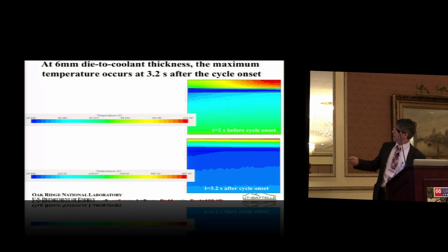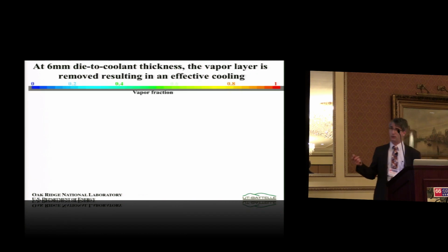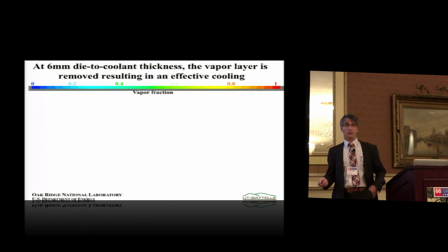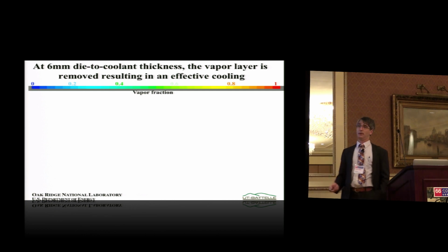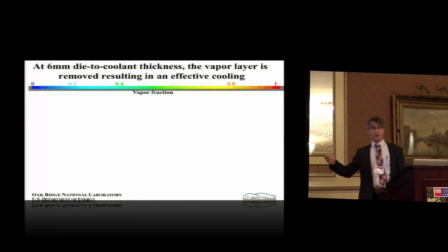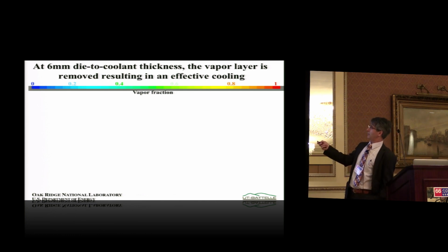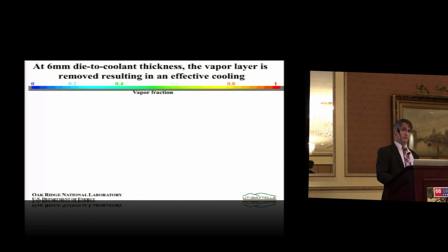For another configuration that we look at, again, here we have a smaller die-to-coolant thickness right here. If you can take a look at these temperatures, we came down from 790, I guess, to about 500. The die can reach up to 600. So it's a very acceptable number. Let's look now at, in this particular case, the last case. Again, color-coded blue is no vapors, light blue, some certain fraction of vapors. The units here from 0 to 1. If you have 1, everything is vapor.